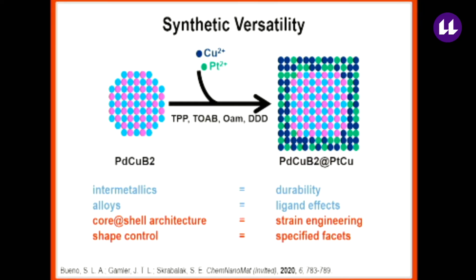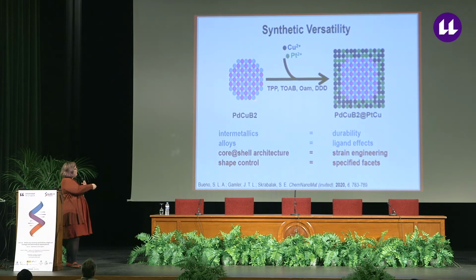And because of this, my group moved out of the aqueous CTAB system and instead considered high temperature organic media to do seed-mediated co-reduction. So we moved into a system based on oleylamine. And our motivation here was a little bit different, where we were interested in designing very durable catalysts, where we were taking, for example, palladium-copper intermetallic nanoparticles and co-reducing metal salts to deposit an alloy around these nanocrystal seeds.